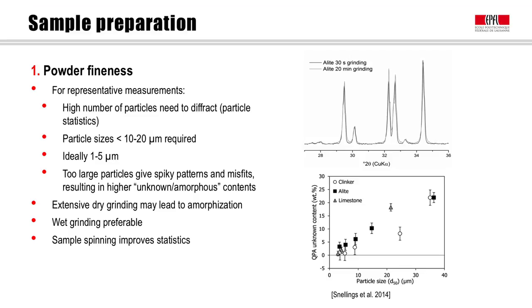However, this is not possible for hydrated cements, where even this kind of treatment may change the vulnerable hydrate assemblage. In those cases, it may be preferable to just gently grind the material and measure it as such, or to actually cut a slice from a hydrated cement paste and measure that fresh. It should also be mentioned that spinning the sample in the horizontal plane improves the statistics enormously, by a factor of about five, so this is definitely to be encouraged in your data collection strategies.